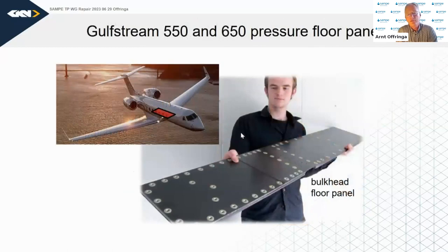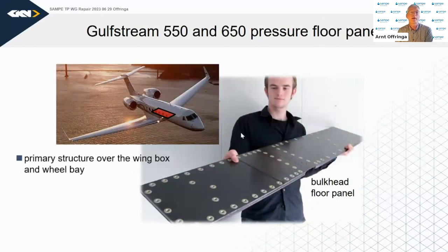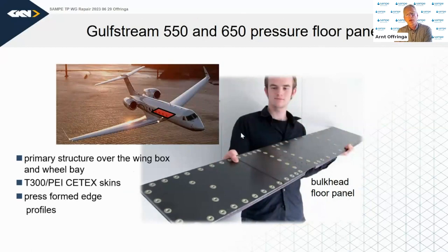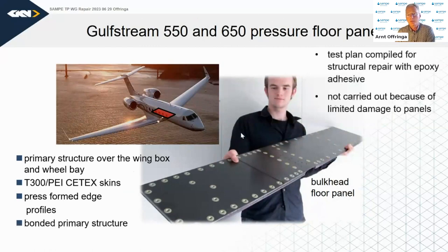The Gulfstream aircraft also have very highly loaded floors in the middle of the aircraft, which covers the hole in the fuselage above the wing. And these floors are a bit thicker. They are bonded together with a primary structure adhesive, and they are primary structures, so they may not fail. It's a T300 Toray fiber with polyetherimide. They include press-formed edges, profiles that are bonded into the panel, and it's a bonded primary structure. So what was done is to carry out a test plan for structure repair with epoxy adhesive. So in principle, it's possible to repair these panels in a structural manner with a bonding methodology. And the reason that's possible is that the polymer, the PEI polymer, the Ultem, is amorphous, so it has truly excellent bonding characteristics. The program was in the end not executed, not necessary, because there's been very limited damage to these panels.